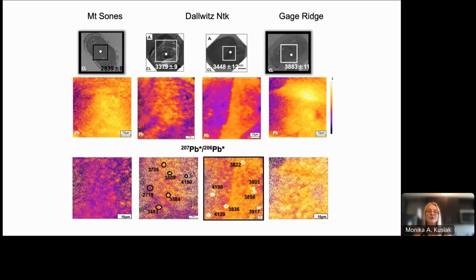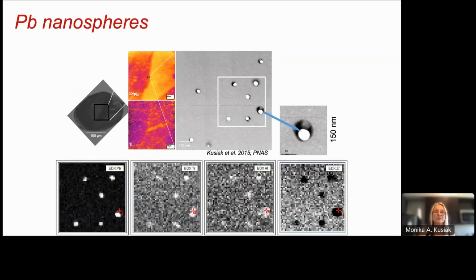One thing which was really dangerous and scary was that when we made simultaneous maps of 207 and 206 lead, and as we know in uranium-lead geochronology, we use this ratio for calculating the age. Using the image tools, we could select various areas of the zircon to determine the age. And in these squares, which are again 70 by 70 micrometers in size, we found that we had 3.8 up to 4.2 billion year zones or clusters or circles or hotspots of ages. But of course, these were false ages, not ages, but just some data. So we took these grains for TEM analysis, and most of my talk from now on will be to show you TEM results.